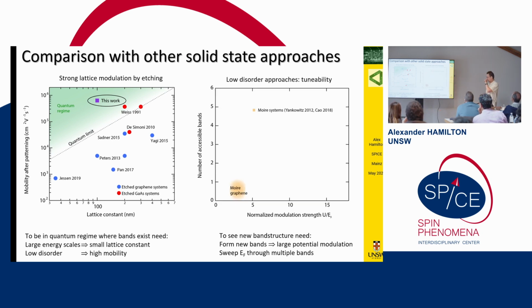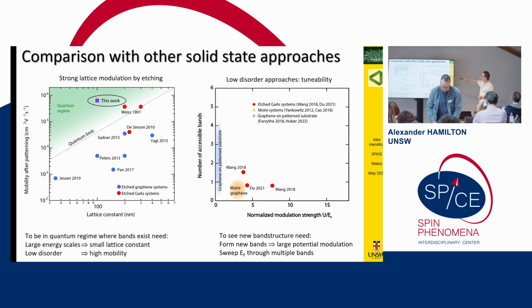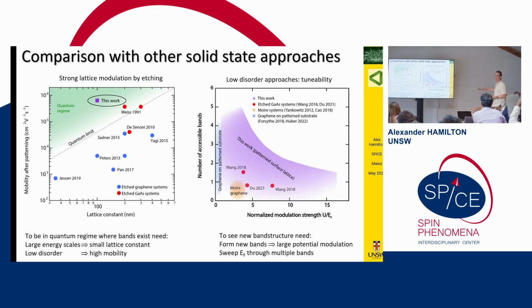And compared to moire graphene, you could look at the number of bands that you can tune the chemical potential through as a function of the normalized modulation strength. With moire graphene, you can go through about one band. The modulation is about a few times the Fermi energy. If you etch gallium arsenide, you can get stronger modulation, but you're still not very tunable. With graphene on patterned substrates, you can get tunability, but at the cost that you don't have strong modulation, and then we can pretty much span everything on that phase diagram.